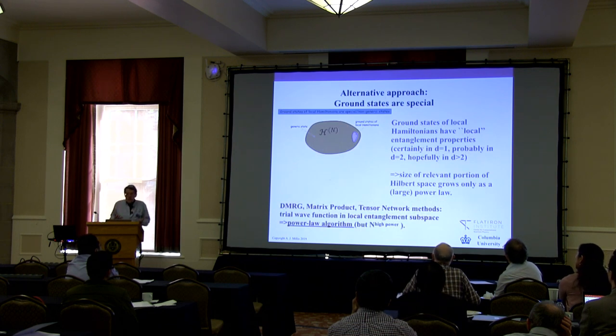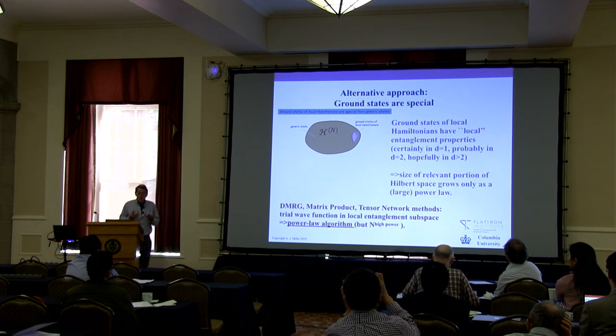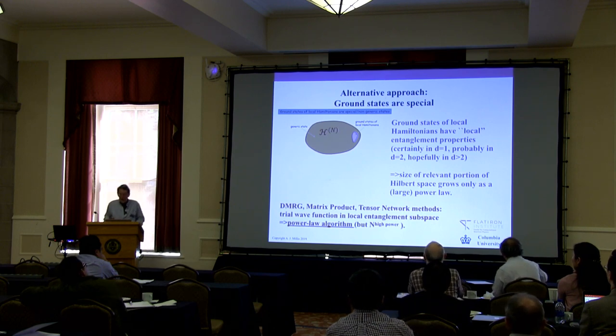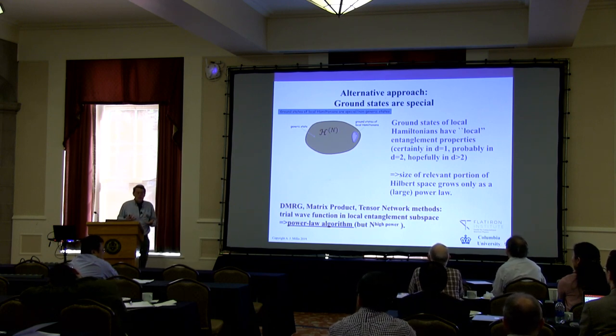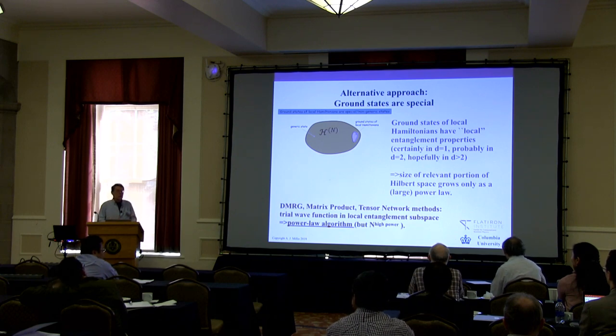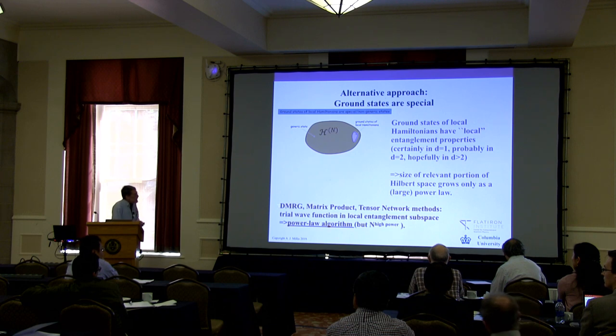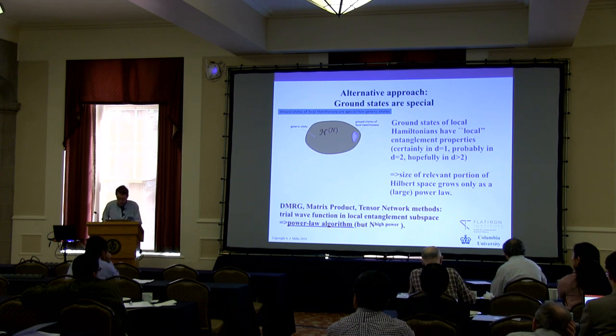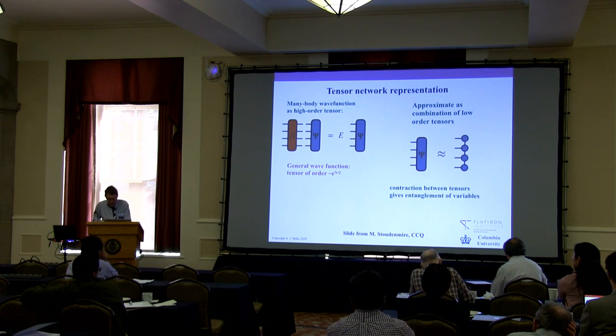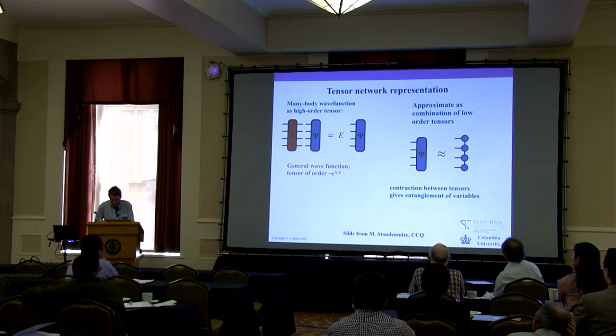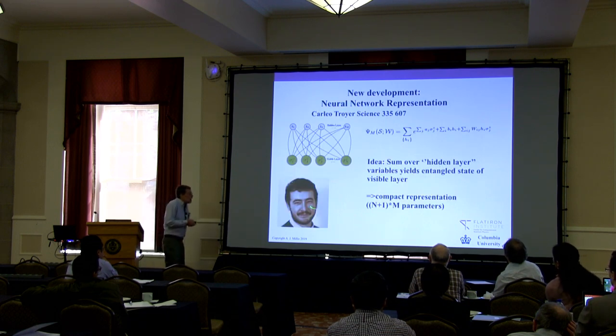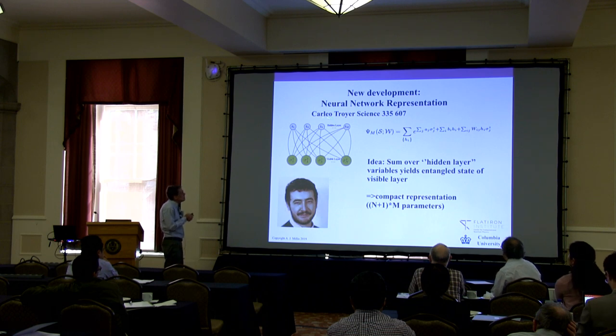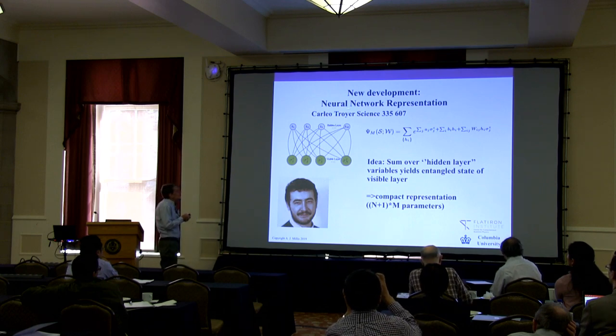Okay, so the number of states which have these local entanglement properties is much smaller than the total number of states. In fact, it grows only as a power law. All right. So what that means is that you, in principle, have a power law algorithm for finding ground states if you could grab on to just the ones with local entanglement properties and use those to build a variational subspace in which you diagonalize your problem. Right. So that is the essence of density matrix renormalization group, matrix product, and tensor network methods. All right. And I'll skip over this except to say that it can be done efficiently by writing things as tensors and breaking up the tensor into lower index tensors. Now there's a new development coming from Giuseppe Carleo, who is now with us at CCQ, and Matthias Troyer, which says that instead of representing things as tensor networks, take ideas from big data and make a neural network representation.